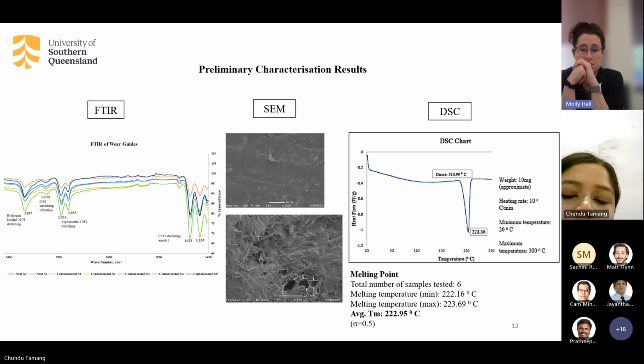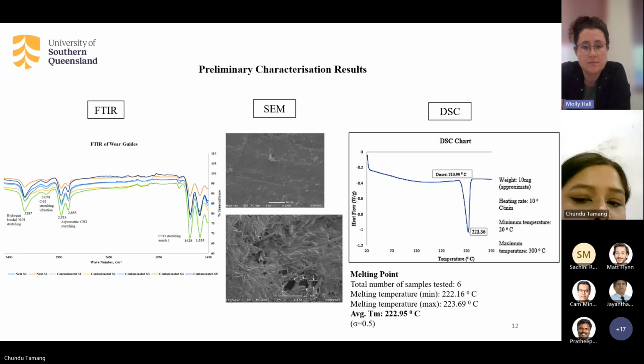But it was the used guides which were found to have significant changes in the morphological properties, and they exhibited an increased degree and rate of surface degradation in the form of cavernous structures and also impurities, which were embedded sand and silt, along with a very irregular surface and complete loss of smoothness and flatness. There were also some wear and tear, represented by breaches, fractures, voids, and cracks. And in the contaminated or used samples, we could also see the exposed glass fiber reinforcement, which was protruding from the polymer matrix.